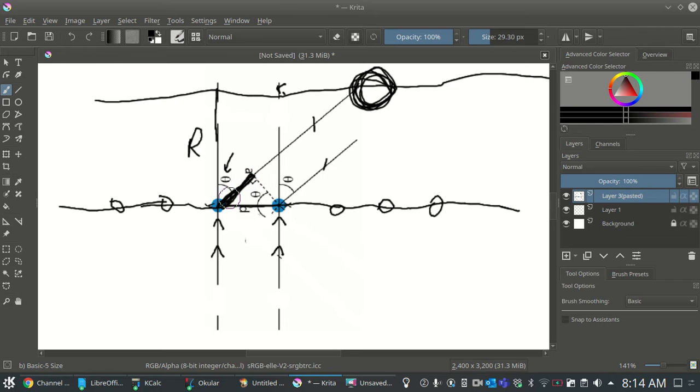This extra length needs to be an integer multiple of the wavelength if you want constructive interference to happen here, all right? And what is this extra length? This extra length is nothing more than d sine theta. So that is why there is no factor of 2 in the 2D Bragg's law, while there was one in the 3D Bragg's law. Man, what a brainstorm, huh? All right.